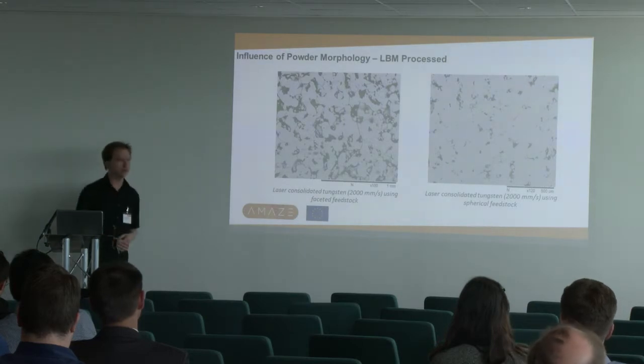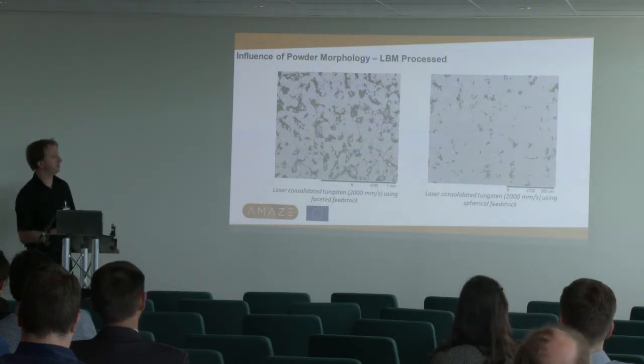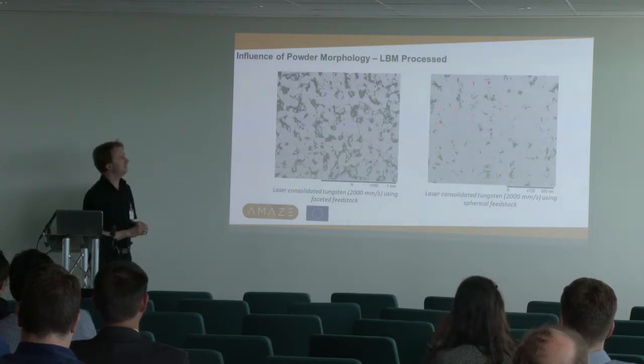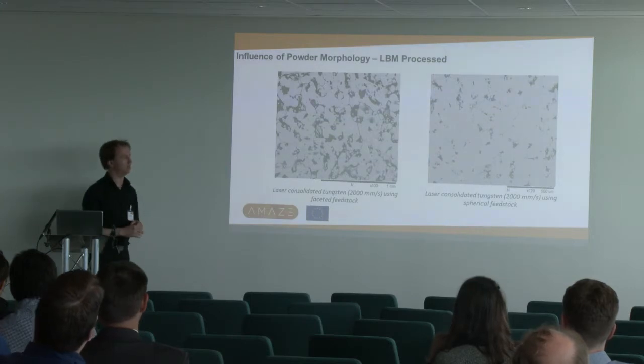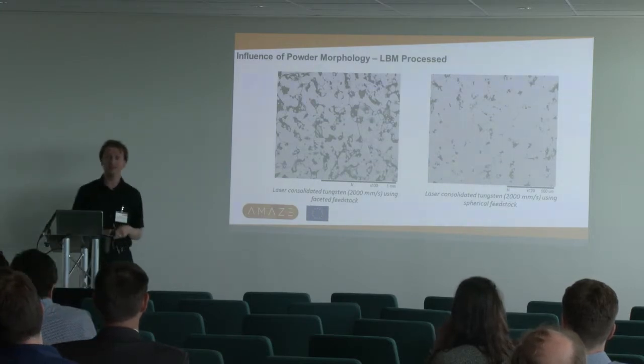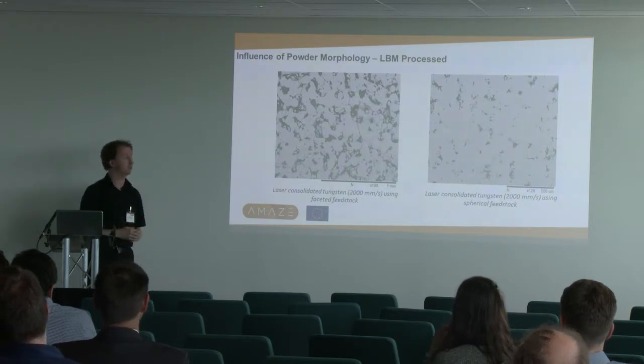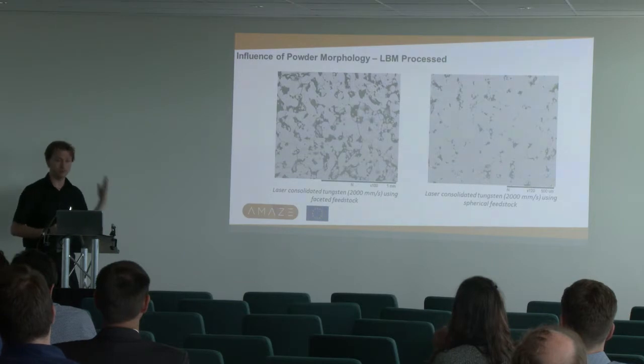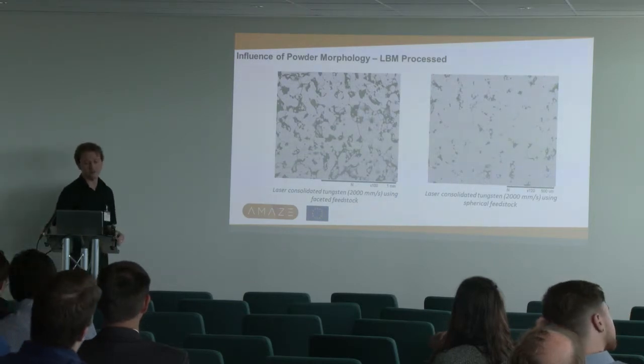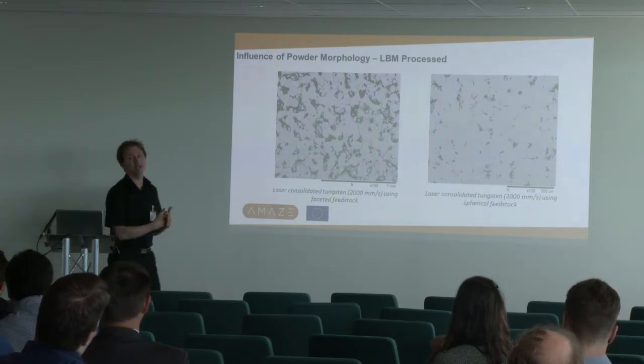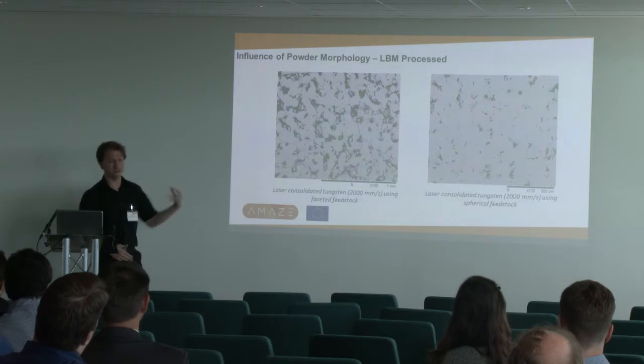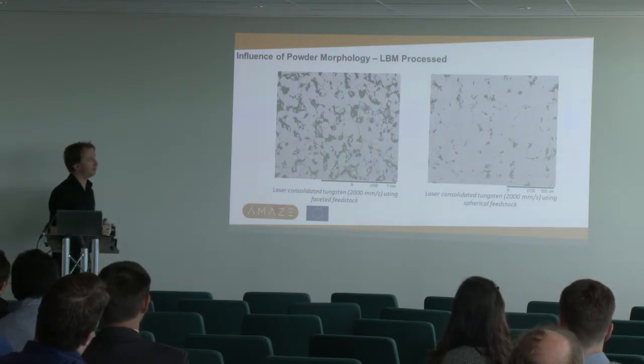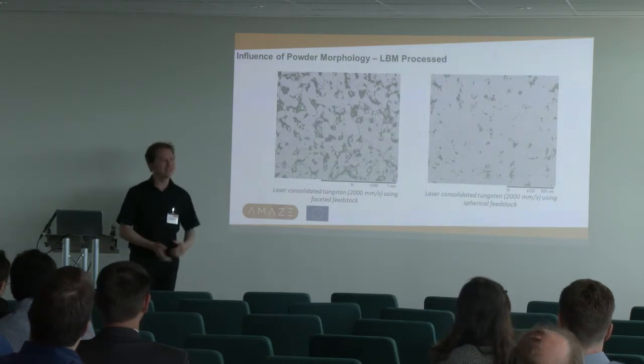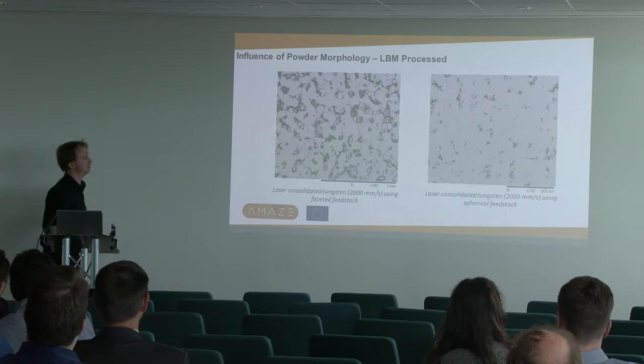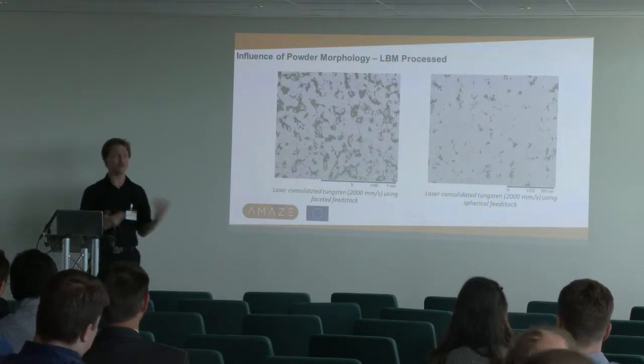Just so you've got an idea of what this looks like, I've put up some micrographs. Micrographs of tungsten currently carry the caveat that it's a very difficult material to prepare for microstructural analysis, especially when it's this cracked. One of the reasons why Amanda stuck with Archimedes density testing is because she had such trouble preparing the material. So some of this porosity that you're seeing here might simply be grains that are being ripped out during the sample preparation process, just because it's so cracked at the grain boundaries. So it is a difficult material to prepare. And likewise, the polishing solution just loves to sit in those pores and then scratch your sample when you're trying to go down to finer and finer levels. So it's a tricky material to work with from lots of different points of view.